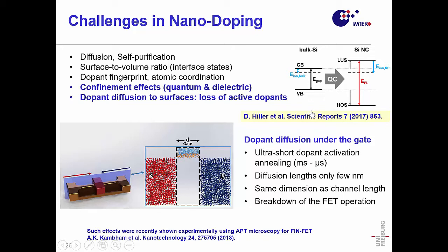The second thing is, just imagine you have implantation, you have these dopants in your source and drain, and then you have to activate them. And that's normally done by an activation temperature of 1050, for instance, for some micro or milliseconds. Think about how far a dopant can diffuse. It should be in a lattice place, and if you're not taking care to think about that, your device might not work at all.